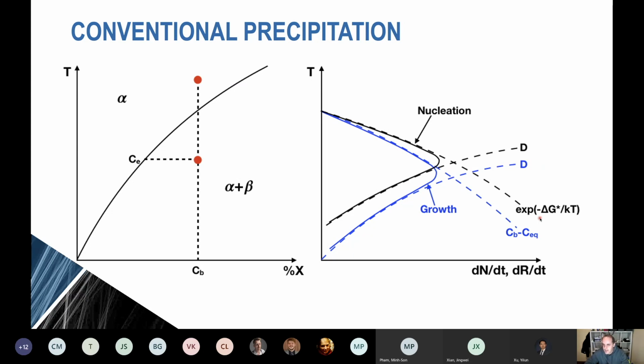But the problem is that in aluminium alloys, these particles have a chemistry that's different to the bulk, so diffusion is also required. It's that competition between thermodynamic driving force and kinetics that gives this C-type behaviour. Now, there's two things to take from this well-known picture that we learn as second-year undergraduate students. The first is that the temperatures that we use to do precipitation treatments in something like aluminium are a compromise. It's a compromise between thermodynamics and kinetics.